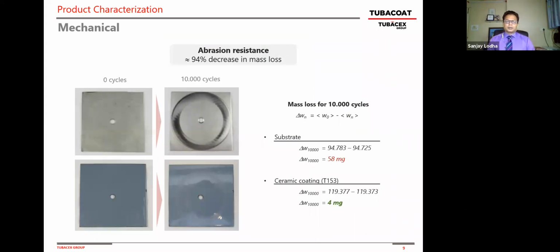How about the abrasion test? So what we have on the screen on my left is the uncoated tube, and at the bottom is the coated tube. And we do an abrasion resistance test, a standard ASTM test with the abrasometer. After 10,000 cycles, when I compare the uncoated tube with the coated tube, we see about 94% decrease in the mass loss compared to the uncoated tube. And that's quite significant. And that's coming from, again, the hardness of the coated tubes. And that's a very important property to have for the critical process equipment. Next slide, please.